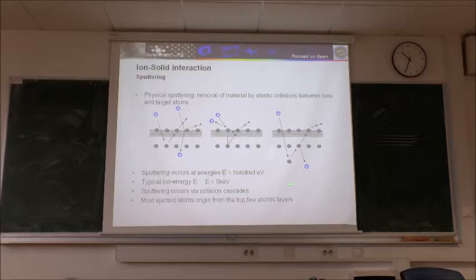And sputtering occurs through a collision cascade. On the next slide, we'll see an example of such a cascade. But what is important is that most ejected atoms or ions, secondary ions, come from just the top few atomic layers. And this is the idea of one method, if you remember, SIMS, secondary ion mass spectroscopy, which is a surface technique. It's very sensitive just to the surface, and also the detection limit is very low. You can detect a few atoms.